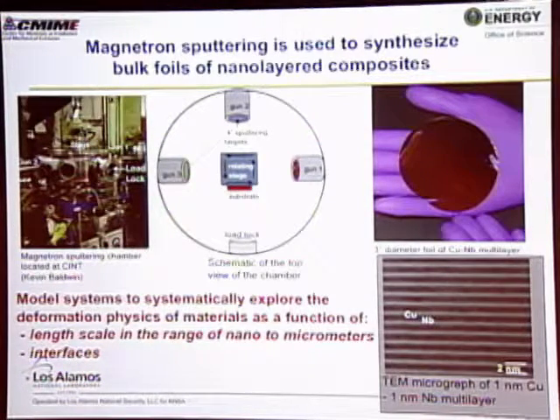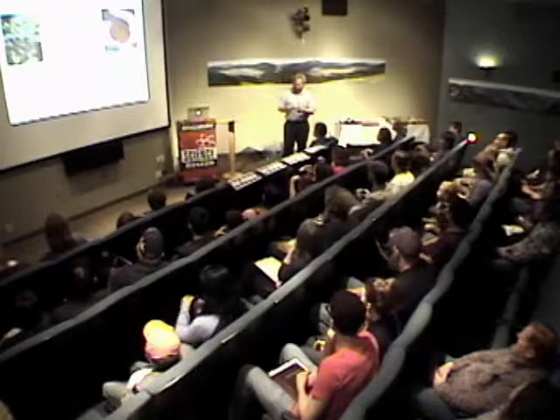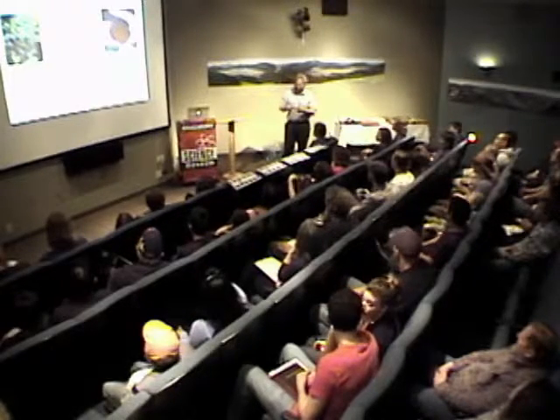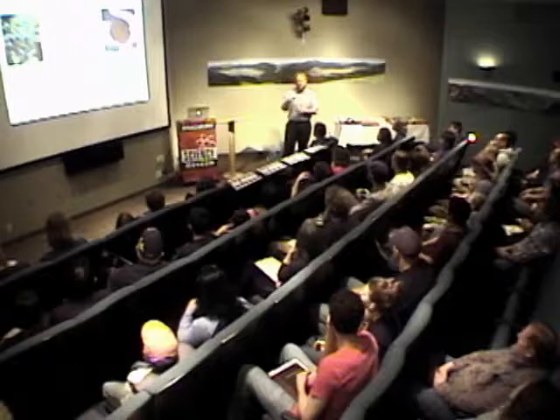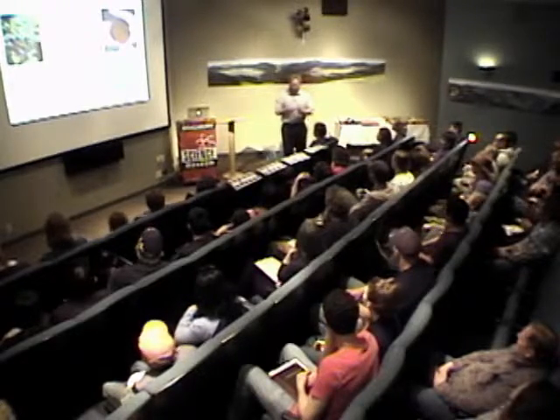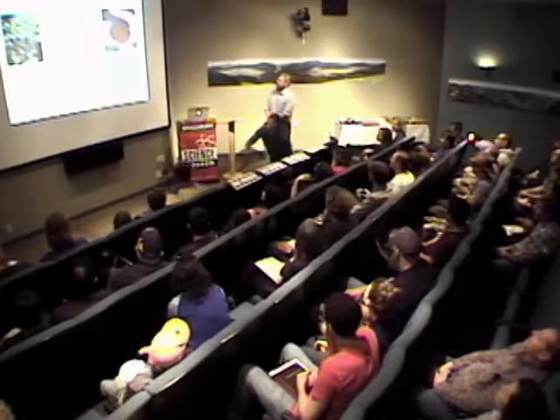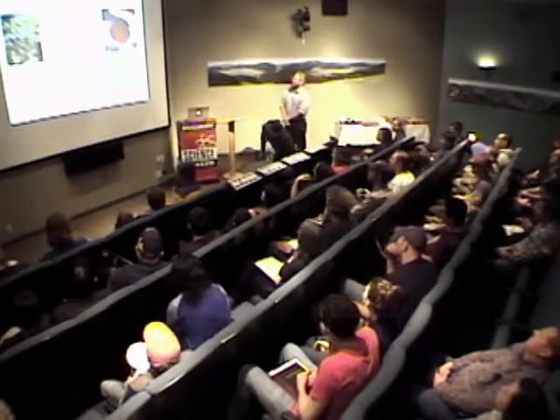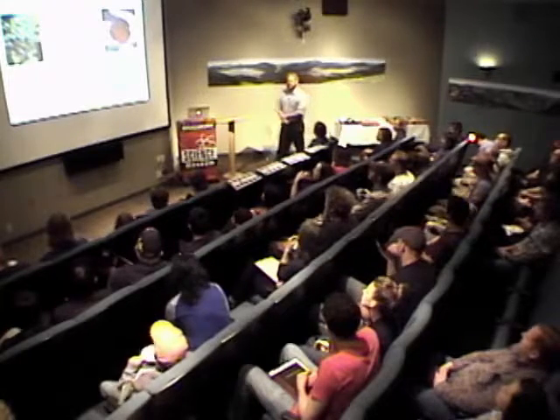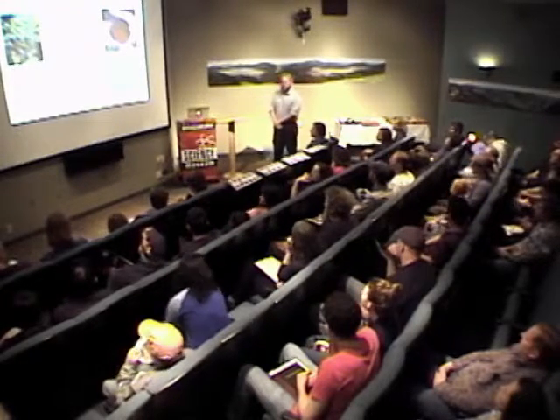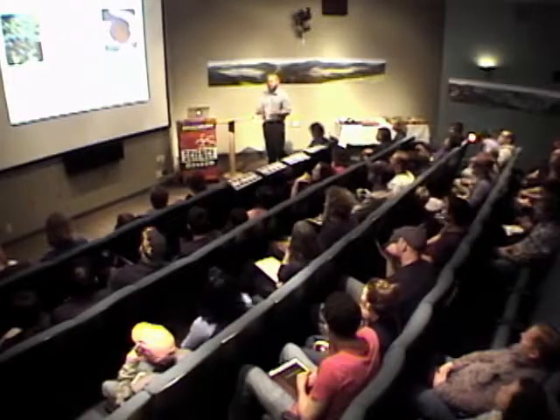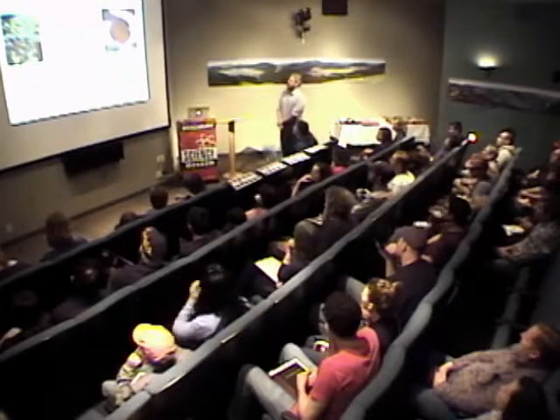like this. So I can actually pass one of these around. This is a 20 nanometer individual layer thickness film with 1,000 layers. So it builds up a foil that's 20 microns thick. And so this is actually sitting on a silicon substrate that we've detached the foil from. So you can take a look at that. So you can see that we do get a material that you can use as a hard coating. You can do small scale tensile testing, micropillar tests. We'll talk about what those are in a minute.